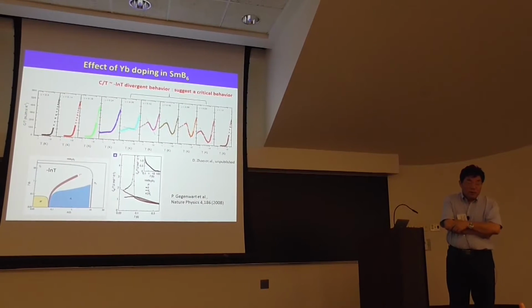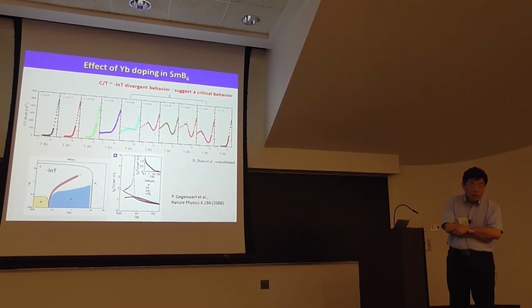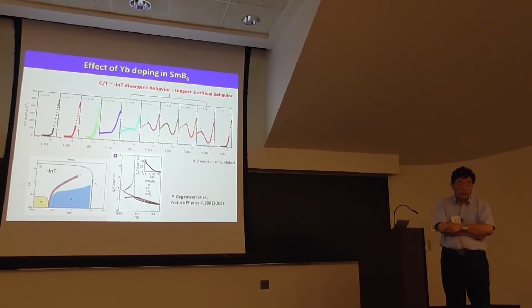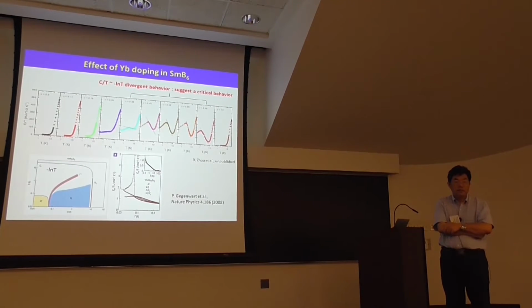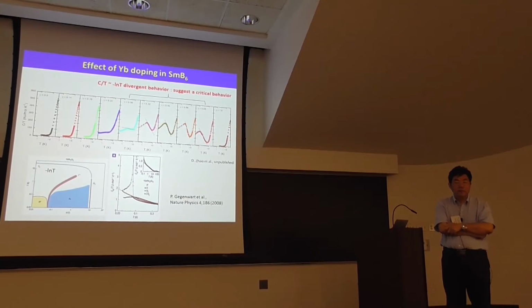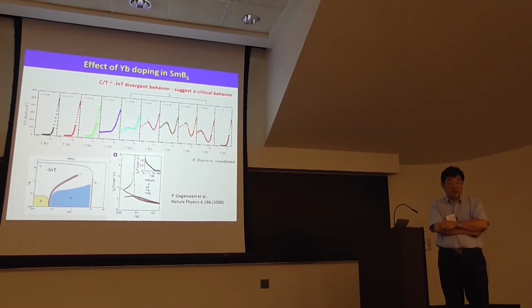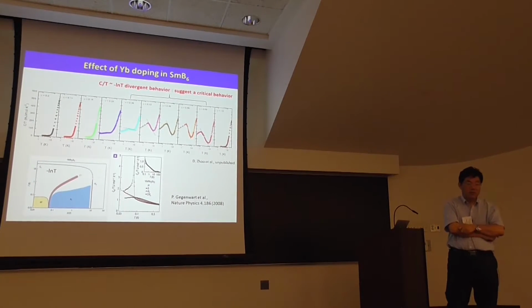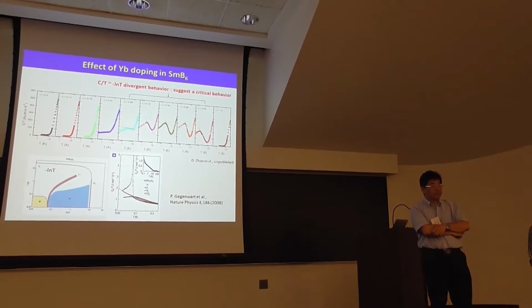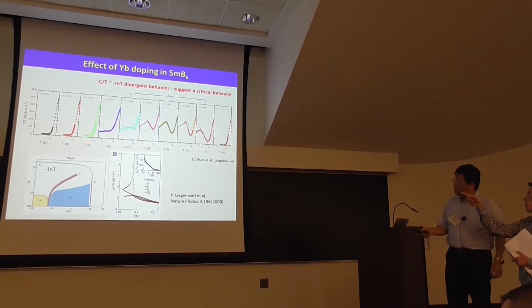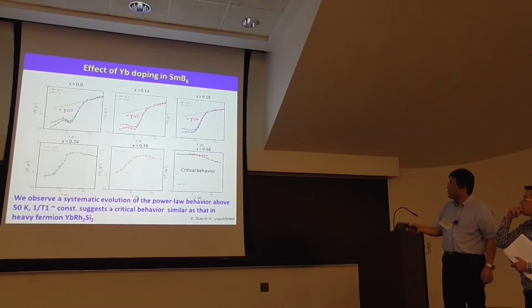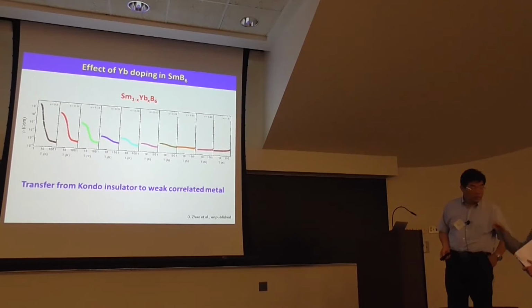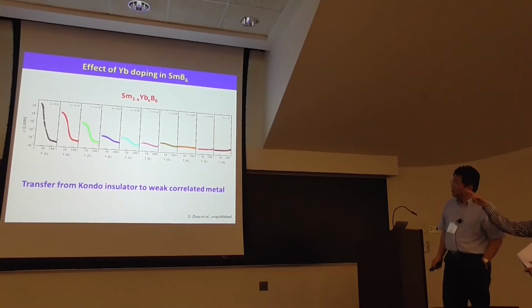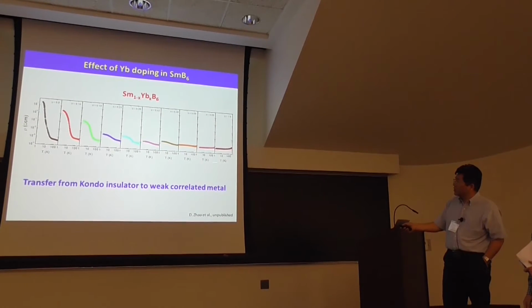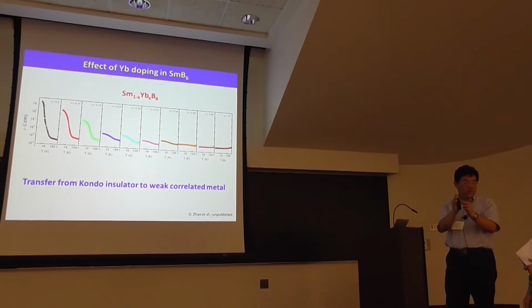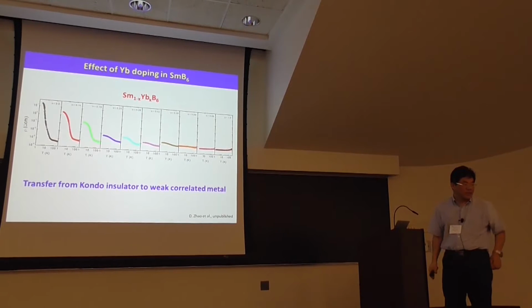What about the Samarium? You suggested that you can change the Samarium valence by adding ytterbium or lanthanum. Is it known that the actual Samarium valence is changing, or are you talking about just the average measurement, like from a susceptibility? Here I just give the average. Average, yes. You still see the saturation at low temperatures. Low temperature, yes. Because here we plot the temperature on a log scale, so from 2 Kelvin to 4 Kelvin is very close.